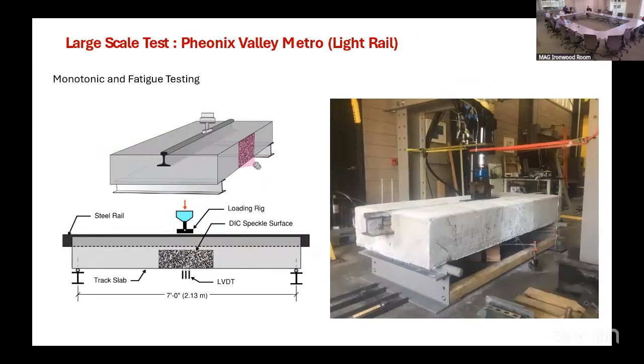So basically the idea was making these mock-up samples, bring it to the lab, set it up, and actually just run the test. But the test had the criteria of 45 years service under the serviceability load design. How do you simulate the movement of a train for 45 years? So we made these assumptions as far as doing the calculations that, okay, assume that every 6 minutes you have a train and the metro is operating 18 hours a day, and assume that you fill it up with 3 times the capacity at every single time.